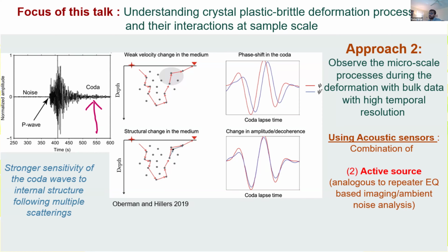The key concept that I'm going to try and test in the work I'm going to show is the idea that the coda waves are a lot more sensitive to the internal structure as opposed to the direct P wave arrivals. The conceptual reason is that the coda waves are because of multiple scattering in the medium, so they have a lot more volume sampling, as opposed to P wave arrivals that tell you about the direct path between the source and the receiver. Since the coda waves scatter multiple times, they're also more complicated to understand and analyze because you don't quite know which exact location they're going through. Whereas with the P wave arrivals, we have a more direct idea: you have the source and the receiver, what's the shortest path.